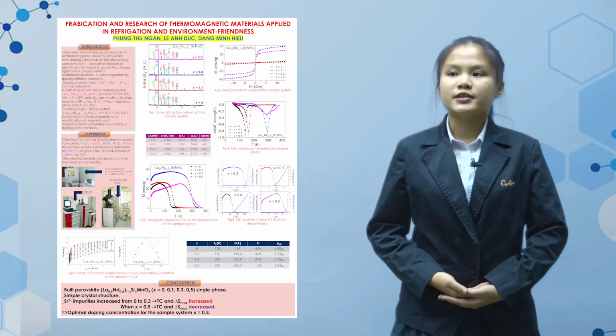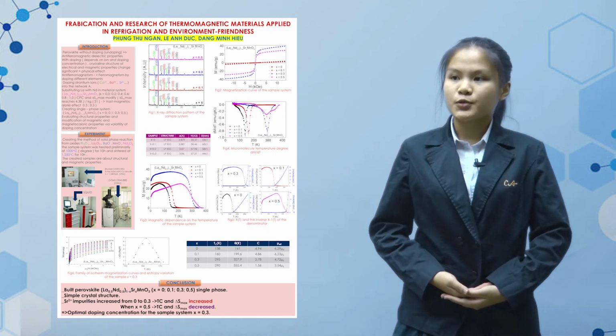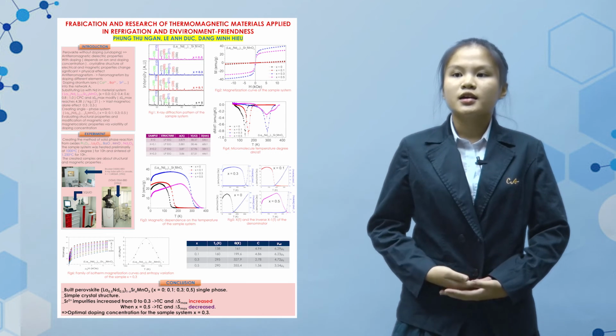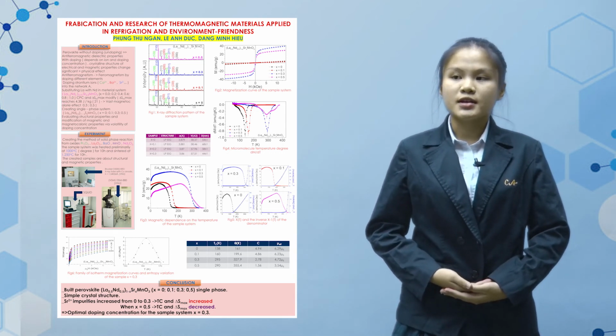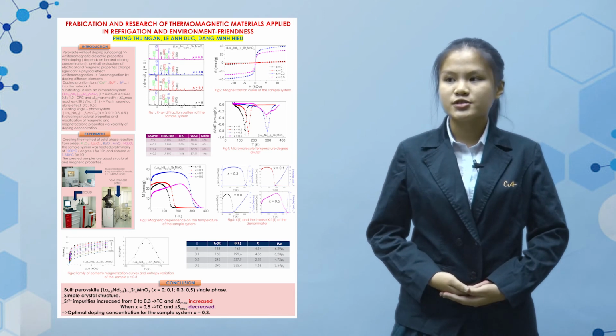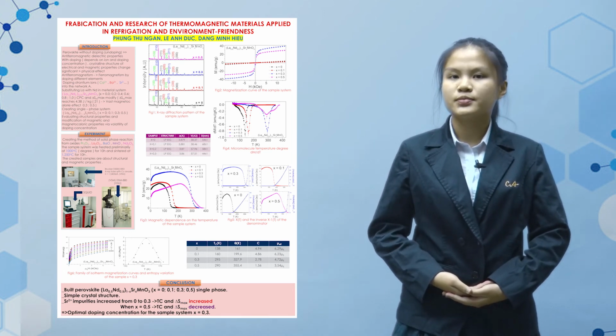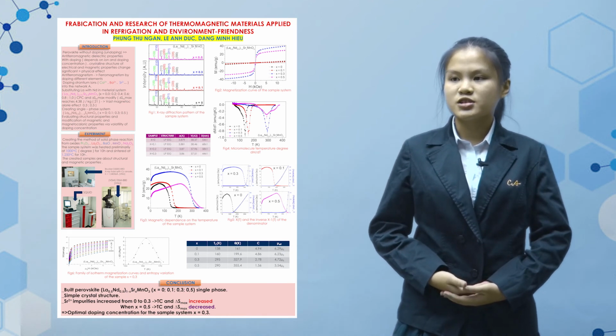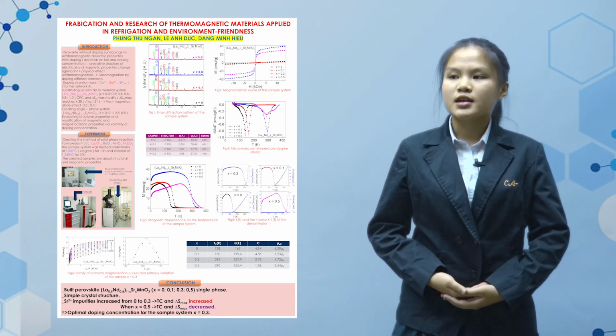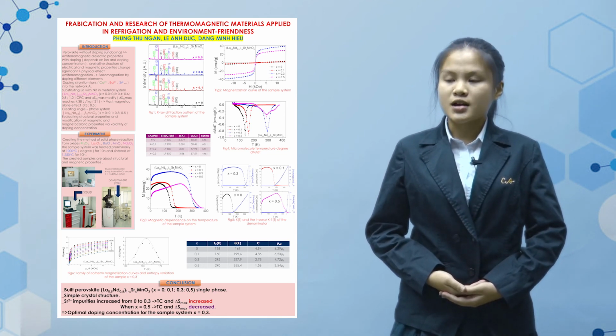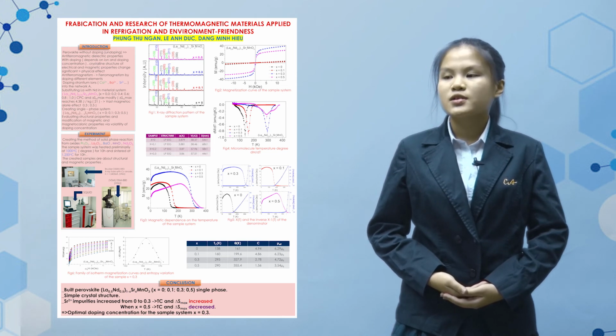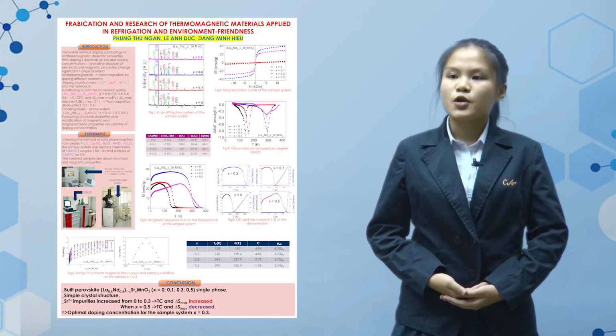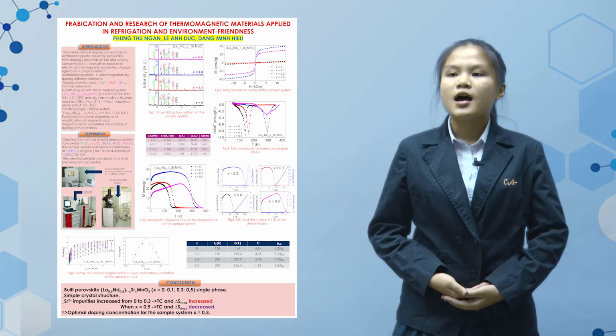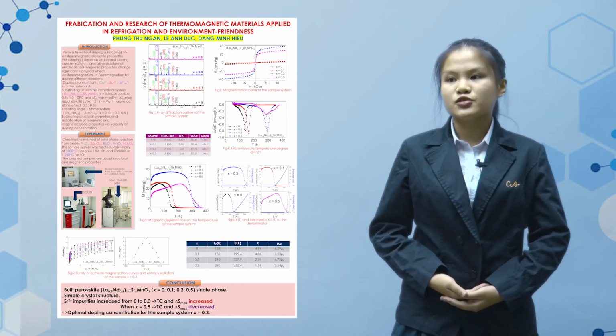From the M-T curve, we can determine kappa T and kappa minus 1 T of the sample system in Figure 5. Figure 6 is the family of isothermal magnetization curves and entropy variation of the sample x equals 0.3. As we can see, the highest fluctuation of magnetization is between 287 Kelvin and 308 Kelvin. So we can determine the highest Curie temperature is about 295 Kelvin. The transformation in linear shows that the higher the changing magnetization, the higher the changing entropy delta S. And delta Sm is one of the values for refrigerant or cooling.